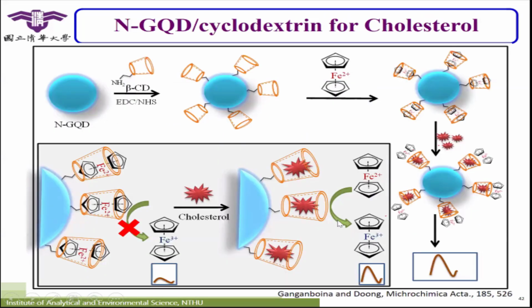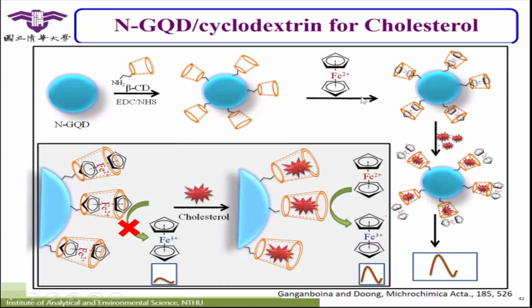You can also use the GQDs added with beta cyclodextrin to detect cholesterol. Here is the case. You have the GQD with beta cyclodextrin on the surface, and if you have ferrocene, it can be here. If you have cholesterol, it gets inside the cyclodextrin and replaces the ferrocene. So the peaks, the electrochemical properties, change dramatically. From these electrochemical properties, we can detect the cholesterol quite easily.